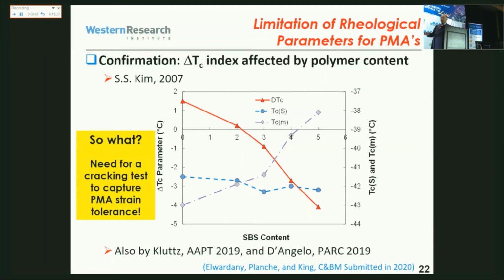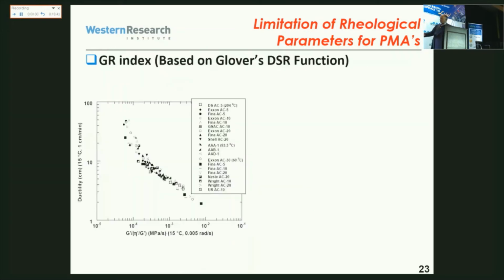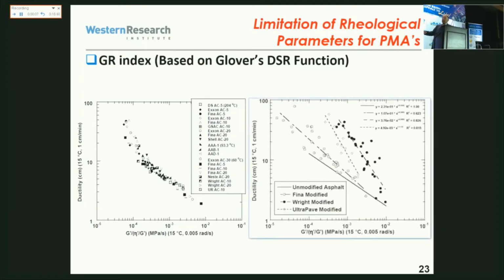And by the way, the asphalt binder is, to my knowledge, the only material in the world which is not characterized in terms of cracking. Why? So we're trying to address that. We looked at other parameters like Glover-Rowe, and the Glover-Rowe parameter does not work at all for polymer modified asphalt. That was presented by Charles Glover himself. So there is no relationship between cracking and Glover-Rowe for polymer modified asphalt. It works fairly well for unmodified, but doesn't work for polymer.